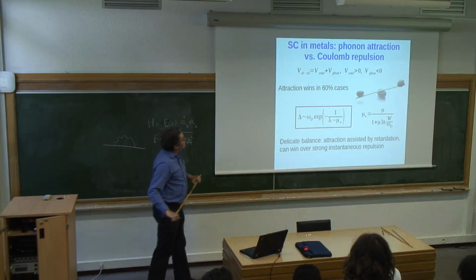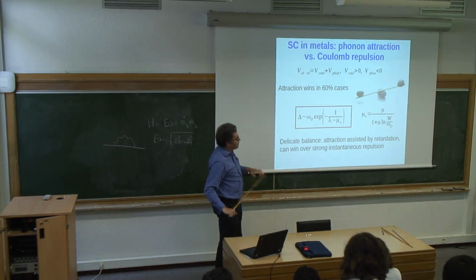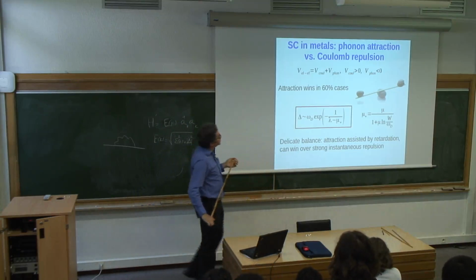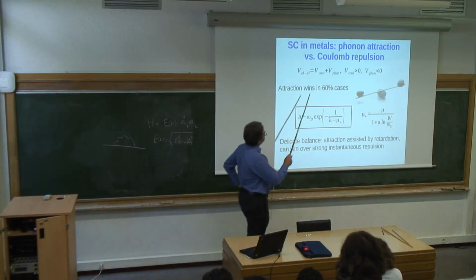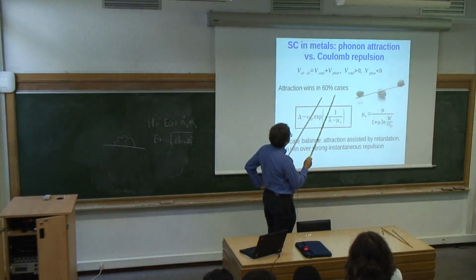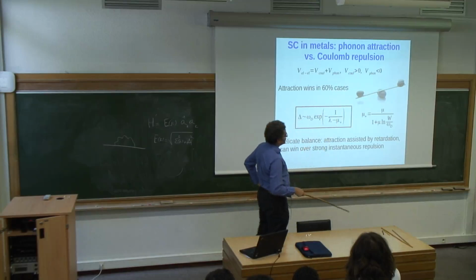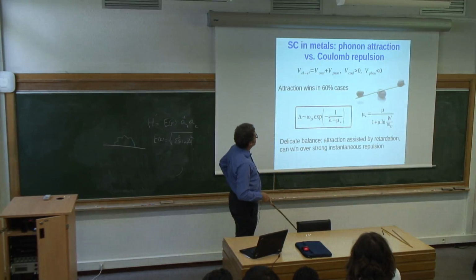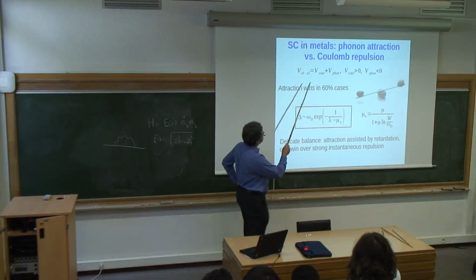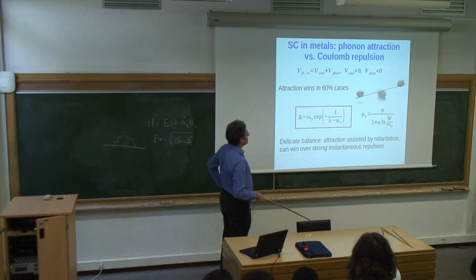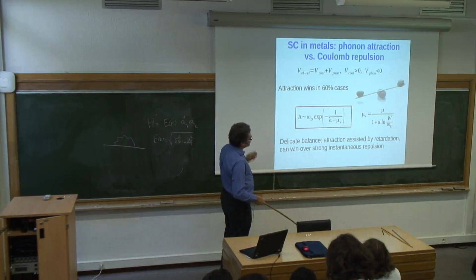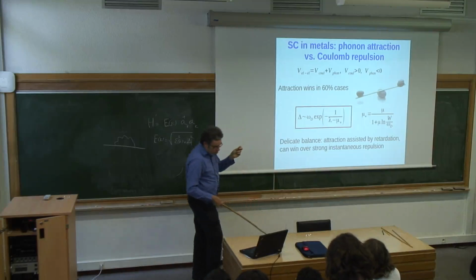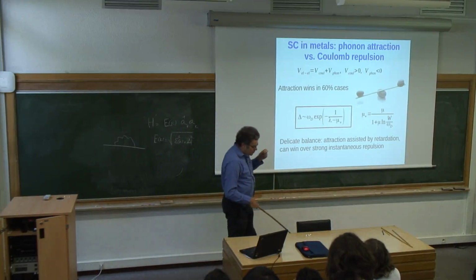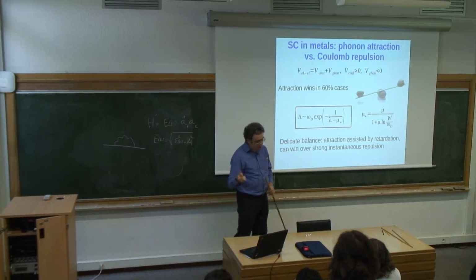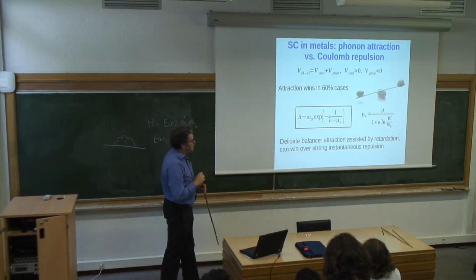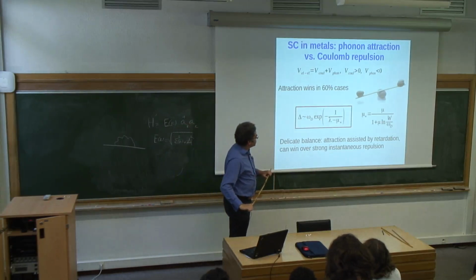So in metals, as we mentioned before, Coulomb repulsion by numbers is stronger than phonon attraction. And if you write a Hamiltonian in which both interactions are present, phonon and Coulomb, Coulomb repulsion is positive, phonon attraction is negative, and one can ask which of them dominates. If you had to decide just by numbers, you would say that Coulomb interaction always wins because it's always stronger. But it turns out that this effect of phonons being retarded and producing some attraction even when the particle has moved away compensates for their relative weakness and makes phonon attraction win in the majority of cases.